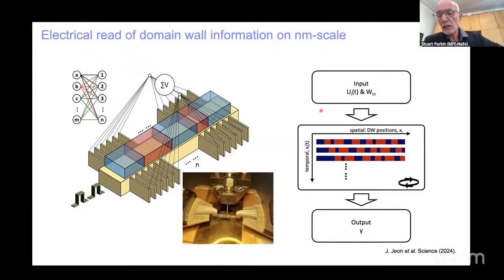So this is some work in particular that was led here by Jae-Chun Jeon, a group leader in my department. And what we did was we built a racetrack shown on the left in this cartoon. This cartoon is to size. So the blue and red regions correspond to a cobalt, nickel, cobalt racetrack magnetized vertically. And the yellow region is the platinum underlayer. So the platinum underlayer here is 5 nanometers thick, and the racetrack is approximately 1.5 nanometers thick.